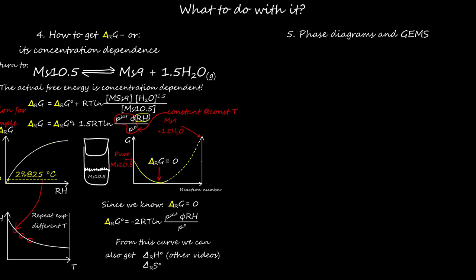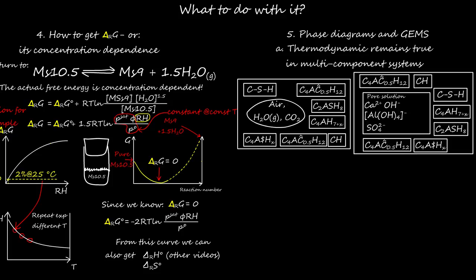We have learned how thermodynamics can be used to comment on the stability of coexisting phases. The power of this method comes from the fact that these statements remain true even in more complex systems, also in the complex cement showed earlier. Now, questions can be asked like: First, most of these solid phases have different hydration states. At a given relative humidity, which hydration state prevail? If we have a given solution composition, which solid phases in cement are stable? This comes from the fact that the same theory represented here is also behind solubility constants. In fact, the solubility constant is proportional to the argument in the logarithm here. Thermodynamic modeling software, like GEMS, can be used with this data to investigate systems which are much more complex than what we have discussed.